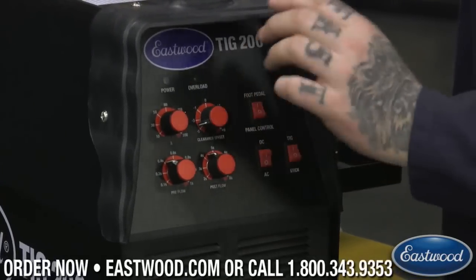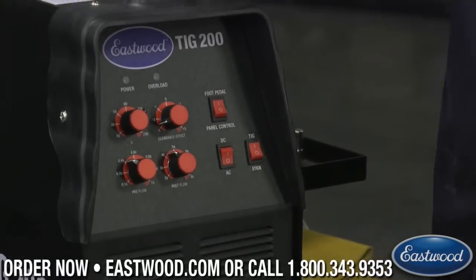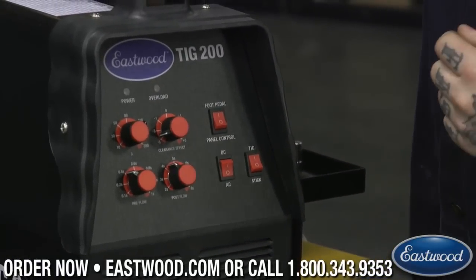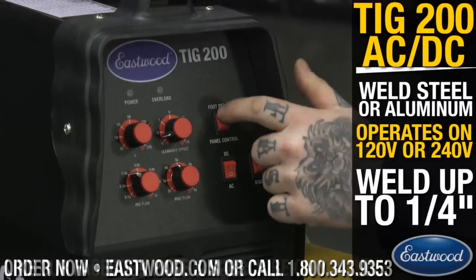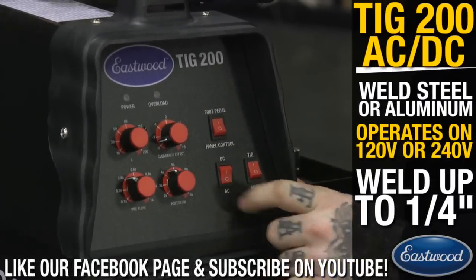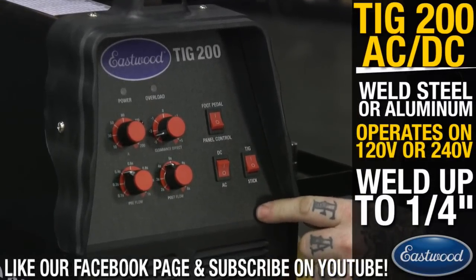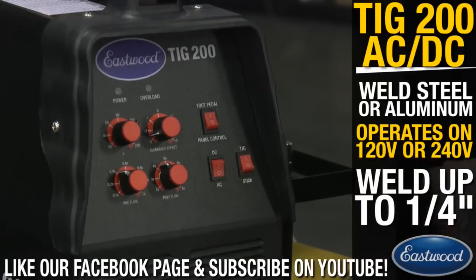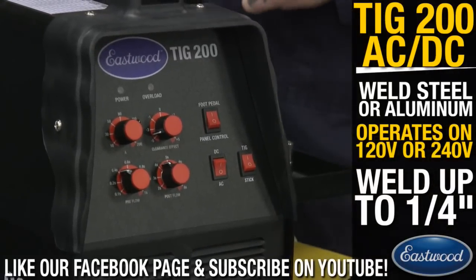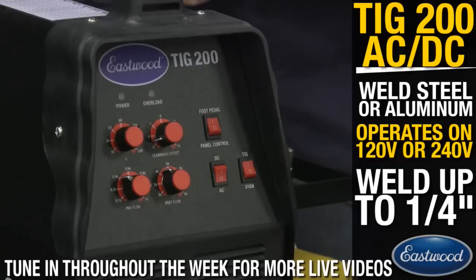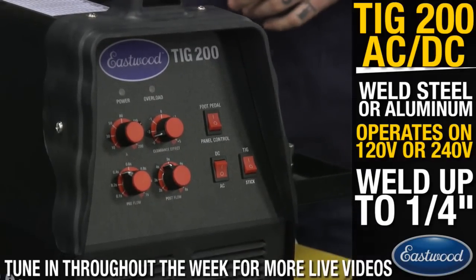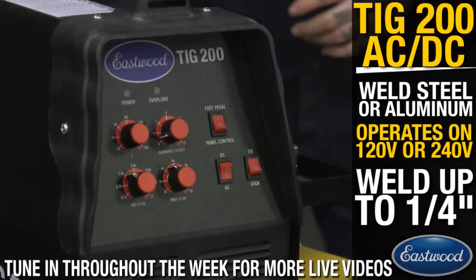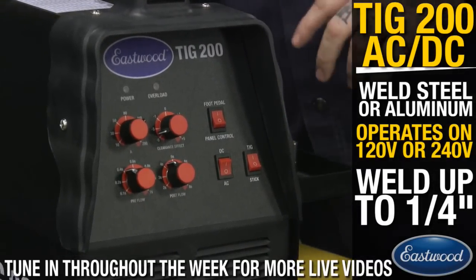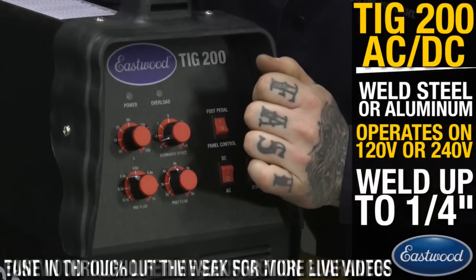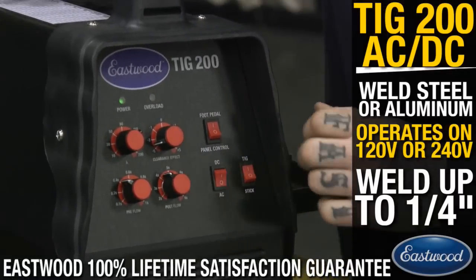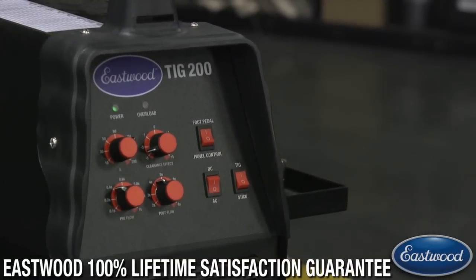Because we're welding some pretty clean metal today, just brand new aluminum, we don't have to go too far to the positive side, and I can keep my cleaning area nice and tight, which will keep my puddle nice and tight too. So I have it on foot pedal. I have the AC side turned on, and of course I have it switched to the TIG because that's what we're doing today. For welding gas, we have 100% argon, so I have that turned on. I have the machine already set up with my clearance effect at -3.5, and all my pre and post flows. So we're going to go over here.